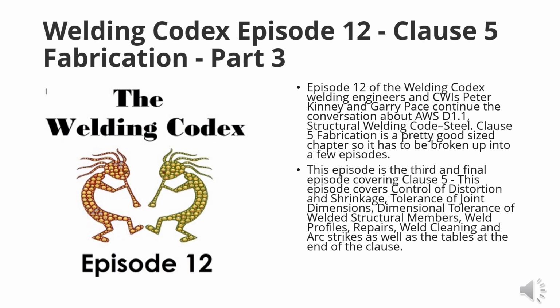So this is just giving you a target here. If you're working with quenched and tempered steels, you don't want to get above 1100 degrees, and then you don't want to get above 1200 degrees F for other materials, because those are 2 temperatures where, without getting too heavily into metallurgy, you get above those temperatures and the game changes on stresses and what you're doing to the material and softening it.